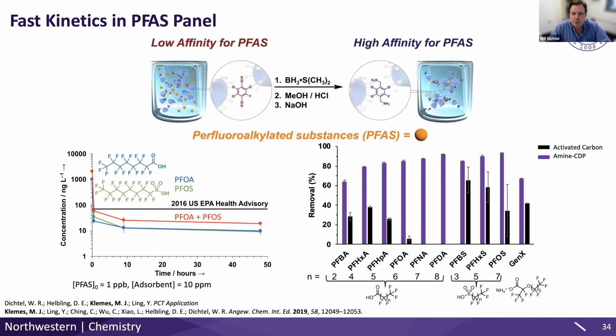Okay, and so we then started looking more into detail about how well these materials could remove anionic PFAS. And so under comparable conditions, first off, these materials are reasonably fast. It's not seconds, but it's certainly minutes that you can approach their equilibrium binding. Relatively small amounts of adsorbents. And so here, the absolute amount of removal is not the most important thing, because you can actually shift that by using just slightly more or slightly less adsorbent. The speed is really, really good.